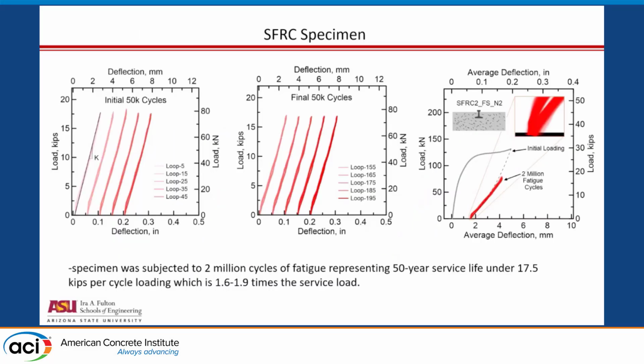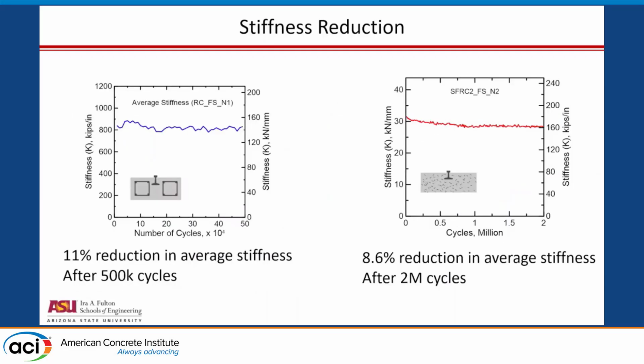So with testing, we go with the SFRC specimen, and we see that the stiffness is pretty much rather constant for various loops. And after 2 million cycles, this is where we are. We went all the way up to about 30 kips, 125 kilonewtons, and then characterized that the section can still carry and has the stiffness to withstand the type of loads that are applied. So again, the stiffness reduction can be plotted, and we see that there is 11% reduction in the average stiffness for the reinforced concrete compared to 8% reduction in the average stiffness after 2 million cycles.